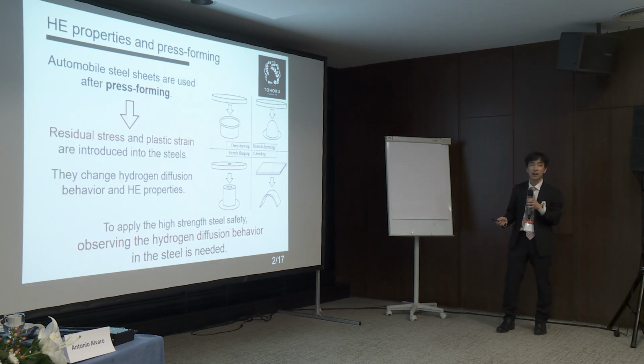Automobile steel sheets are mainly used for body frames, and they are mainly used after press forming, such as the stretch forming written in these schematics. After that, residual stress and plastic strain are introduced into the steels, so they may change the hydrogen diffusion behavior, resulting in a change of hydrogen embrittlement properties. So in order to apply high-strength steel safely, observing the hydrogen diffusion behavior in the steel is needed.